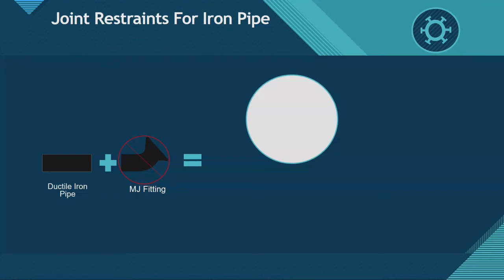A fitting, when it's made, and the next presentation I do coming up after this one shows how fittings are made, goes into a sand mold. The molten iron's poured into a sand mold, and it cools off in there, and the properties are set in the sand mold. There's not near the same control over what those properties are going to be. We know the minimums they're going to be. We can control that, but they might exceed that to a higher degree. So the hardness of this fitting could be harder than the pipe. The problem that comes to is your restraint wedges are designed to bite into ductile iron pipe and the hardness of that pipe. If the plain end MJ fitting is harder than that, the wedges may not bite into it, so you won't get any restraining done there.